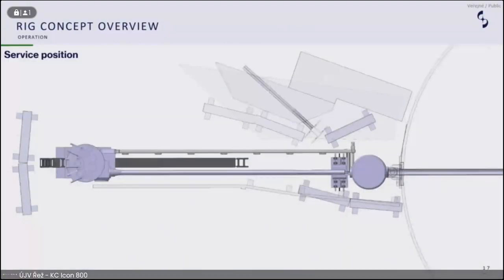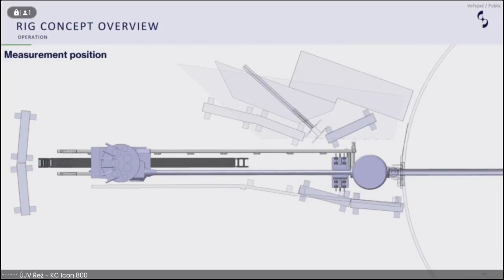What is operation going to look like? Again, I really need to reiterate that this facility allows us so much flexibility to do this. Our sample is within the rig arm - we then cannot enter, we turn our cryostat on, we bring our sample down to 20 Kelvin. We then move our sample to the measurement position, turn the magnet on, and ramp the magnet up 1, 2, 3, 4 Tesla, taking a critical current measurement at each of those points.